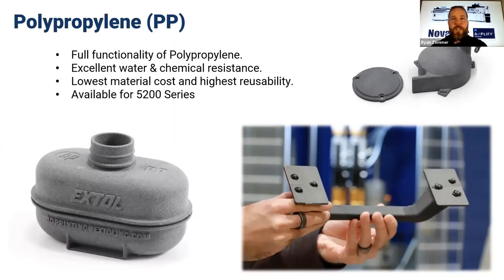So the bottom left is an example of two parts that were hot plate welded together. The weld is actually very strong, stronger than the base material itself. They did some pressure tests on this, and where it failed, it was actually up on the top edge of the container itself. It's difficult to see here because this part was already hot plate welded, but there are interior baffles inside of that, which is kind of the reason why it was done in two different pieces and then